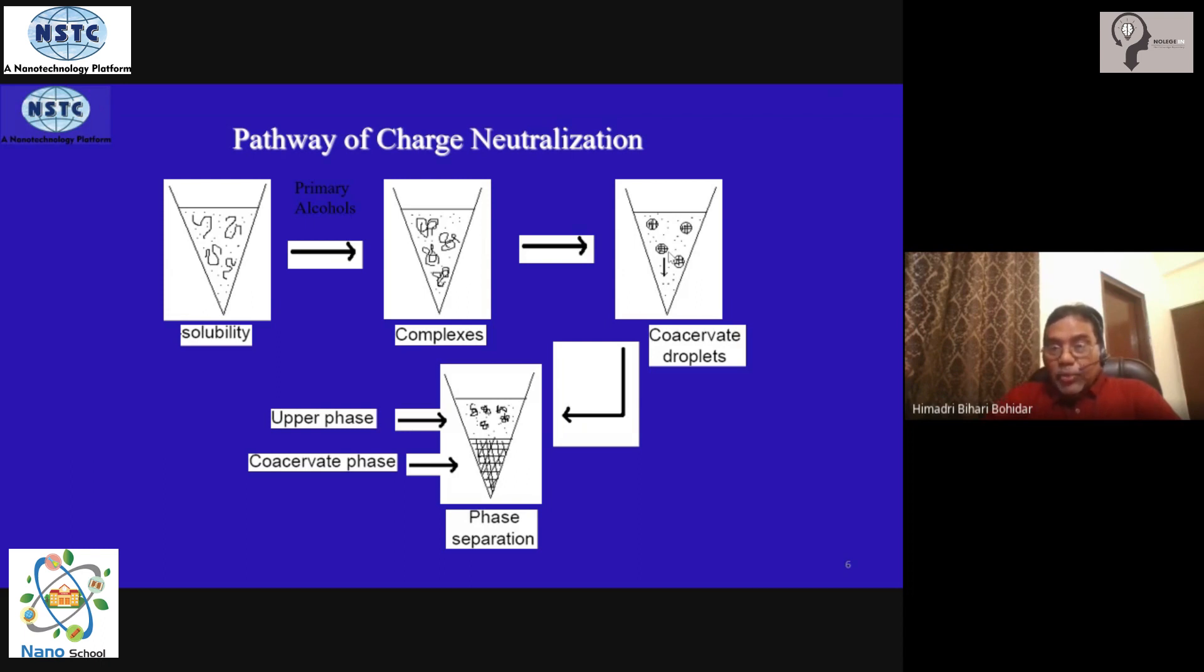Those droplets will undergo coalescence and a coacervate phase will now emerge from this dispersion which is dense. It is going to sit at the bottom of the reaction vessel. Those collapsed particles of the polymer chain which have not participated in the aggregation process will continue to remain dispersed in the supernatant.